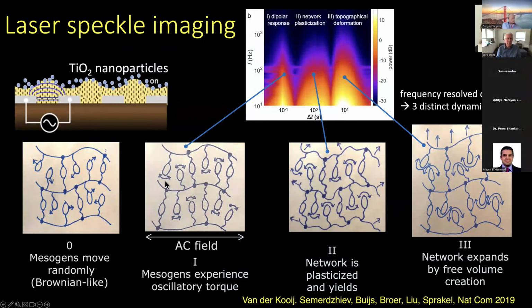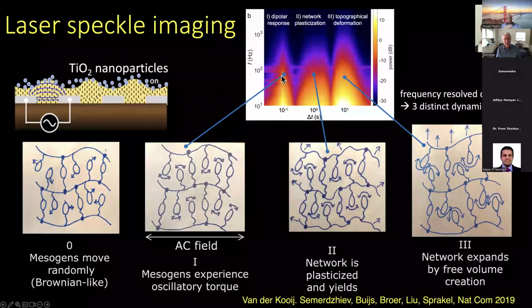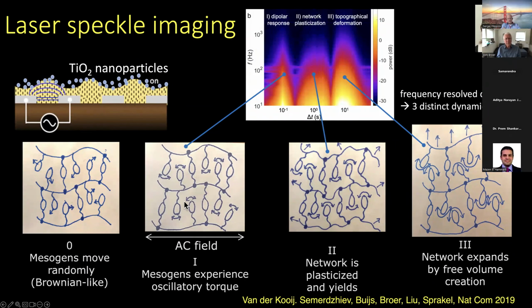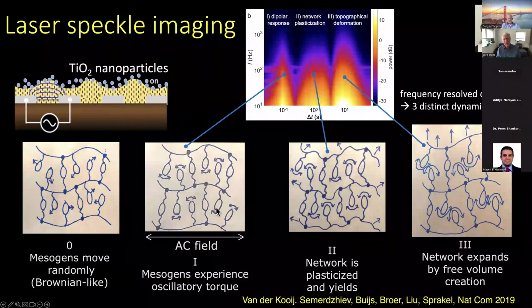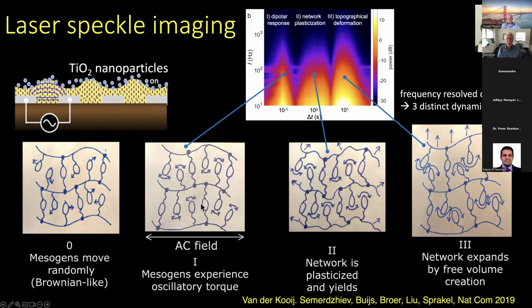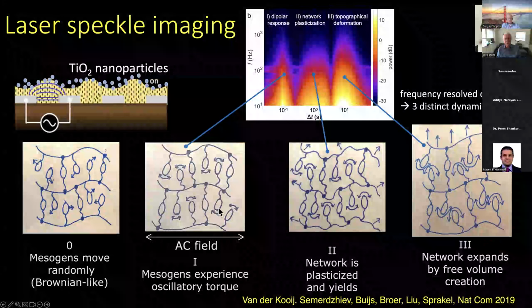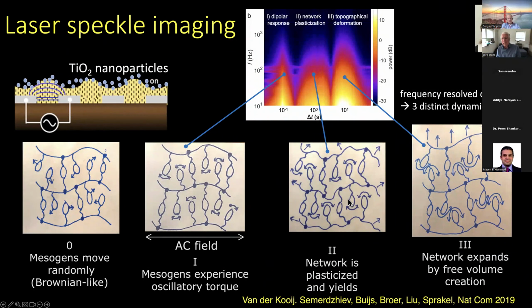We did some laser speckle imaging studies on that, and we could basically, upon the actuation, see 3 regimes. First, if you start with laser speckle, you can get information on the mobility of individual molecules. So basically, if you start, you see the molecules randomly move a little bit, Brownian-like. Like a Brownian motion, but the amplitude is relatively small. Then as soon as you start applying the AC field, you come in a regime where the amplitude of the molecules becomes larger, and slowly the molecules start to create a free volume.